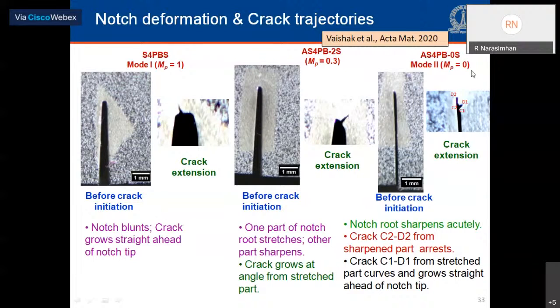In the mode 2 case, there is acute sharpening of the notch tip, and there are 2 branches of cracks which initiate. The portion C2D2 at the sharpened part grows a little bit and arrests, whereas the C1D1 branch initially grows at an angle, then curves around and goes straight ahead of the crack tip.